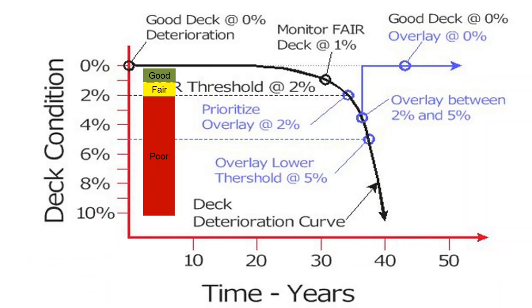This is kind of a key graph. It's kind of a deterioration rate that's based on all our experience. So you can see sometime in the future, especially bridges without epoxy coating, the epoxy coating will shift this graph a little differently. But as time goes by, maybe 30, 40 years, the deterioration will catch up. And then once you hit the threshold of 2%, then we program it for some type of an action, rehabilitation. We're hoping to get that before 5%, because as this curve continues on down, if you let a bridge go to 10 or 20%, then your deck rehabilitation options are kind of gone, and you're looking at some type of a replacement, which is much more expensive.